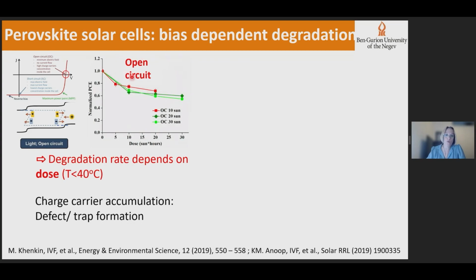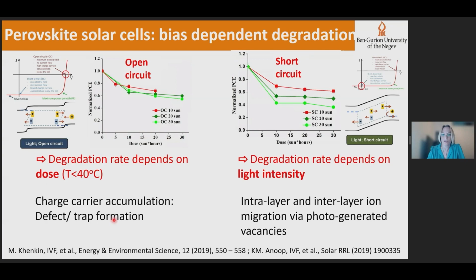And what you can see is that when the cells are stated at open circuit, which is these conditions on the current voltage curve, all curves fall roughly on the same line, even though the red ones were measured at 10 suns and the green ones were measured at 20 and 30 suns. So different light intensities, but really what counts is the dose. If you think about it and you consider which mechanisms can be affected by bias and are pointing to or related to accumulated damage, then we can come to the point that charge carrier accumulation is an accumulated damage that contributes to defect and trap formation. This is probably the dominant degradation mechanism under these conditions.